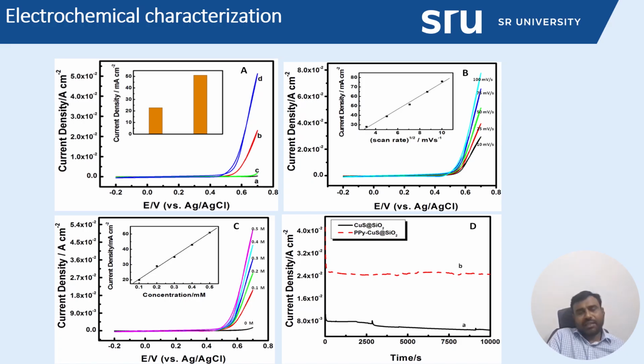in alkaline condition. It is known that a metal in alkaline condition may form the corresponding hydroxide, or it may leach slowly into the solution. To avoid this, polypyrrole acts as a protecting layer, and it also has small pores. Methanol easily penetrates through the pore structure and accesses the active sites of the copper. So this enhances the oxidation current we have observed over the polypyrrole coated copper sulfide hollow structure.